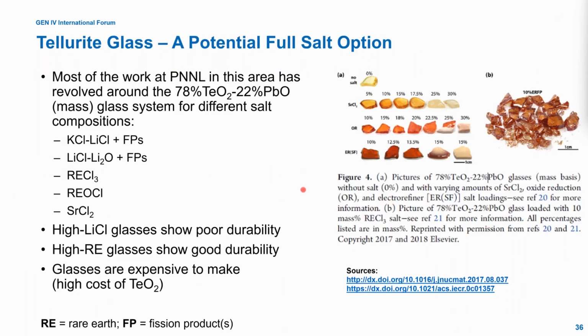Tellurite glass is a very unique glass system that we've worked with here at PNNL that you can use to dissolve various different salts. What we found is that even though the strontium chloride, the lithium chloride, lithium oxide, and then the potassium lithium chloride with fission products, these particular glasses, while they look single phase, there's very incongruent dissolution that occurs. And so with the high alkali tellurite glass, the durabilities aren't very good. But when we start looking at things like rare earth chloride immobilization, these particular glasses were single phase and had very good chemical durability. So these are an option. I say a potential option because they're very expensive to make. TeO2 is very expensive because it's a very rare compound. So I don't know how plausible this would be to implement, but it is certainly something that could be considered.